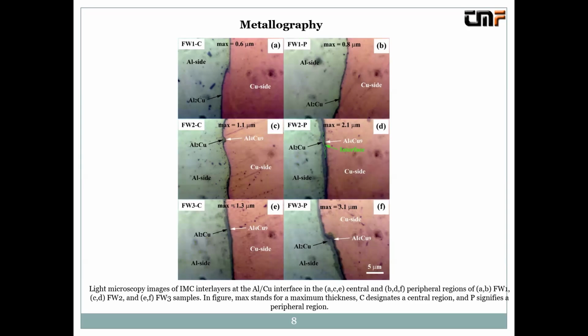solid joints. So during the metallographic analysis of the welded joints, we could distinguish that, for example, for the shortest friction time, we obtained AlxCuy intermetallic compound on the interlayer between aluminum and copper. So what's the importance of this? Maybe it's hard to see from these pictures, but the intermetallic layer is not continuous. It has variations of thickness and also discontinuities.